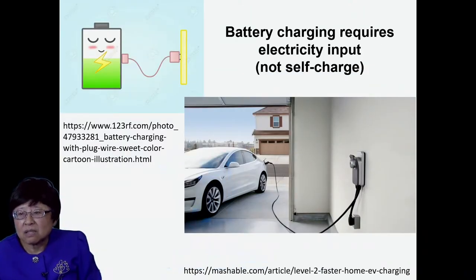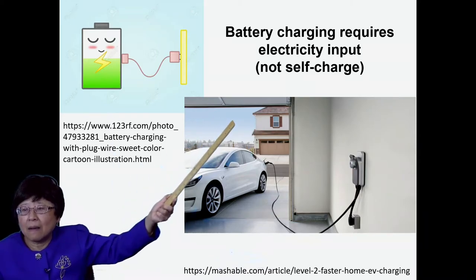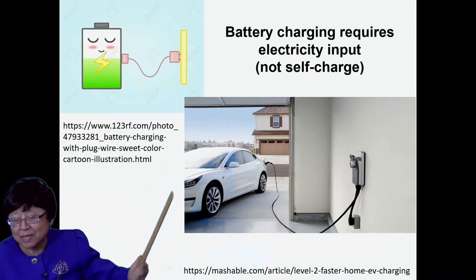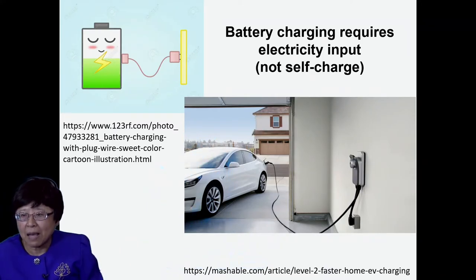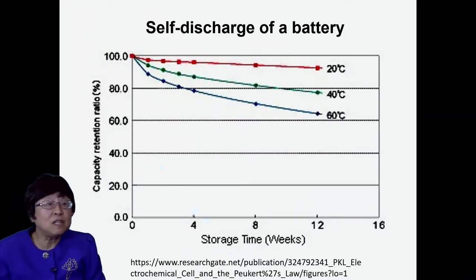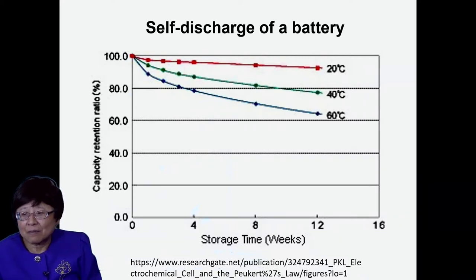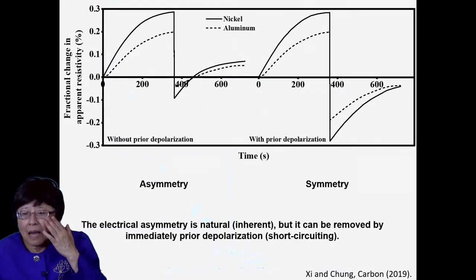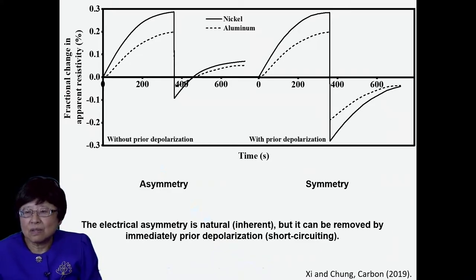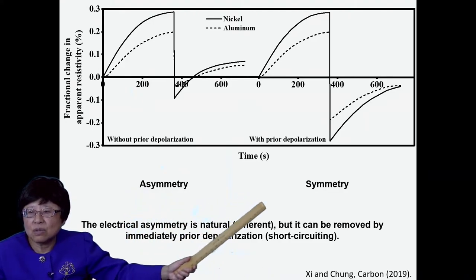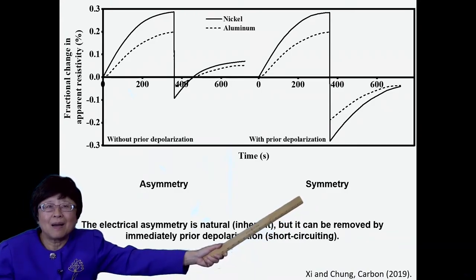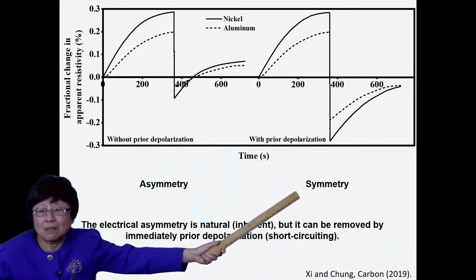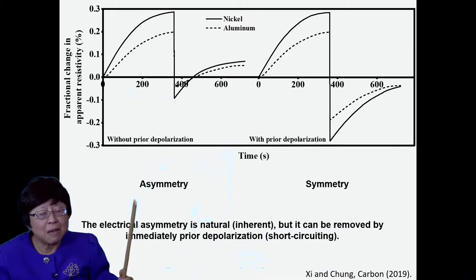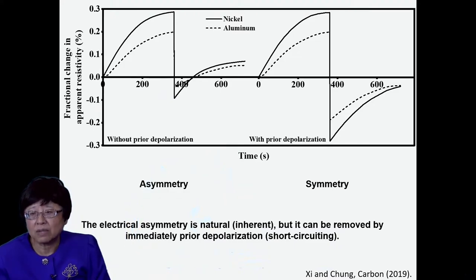Battery charging requires electricity input, right? It's not self-charge. Batteries cannot self-charge. You have to input electricity in order to charge a battery. But a battery self-discharges. If you let it sit for some time, the voltage becomes lower and lower. The electret in conductors is consistent with this asymmetry. That's natural. As I said, in order to make it symmetric, you have to brute-forcefully short-circuit it for, say, 6 minutes immediately before testing. Naturally, it's asymmetric, and that points to the presence of an electret.